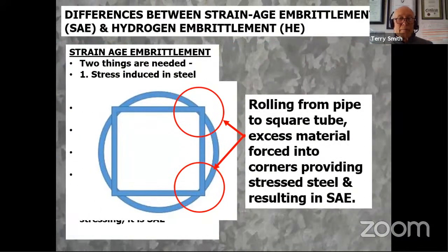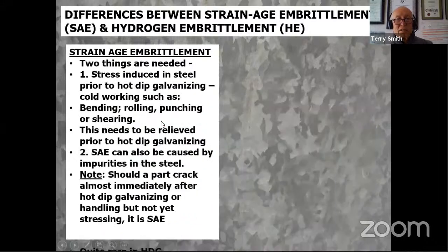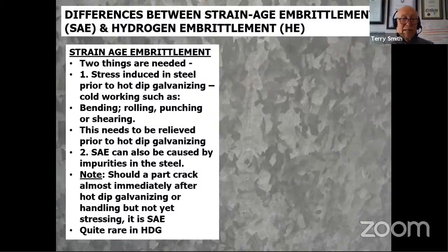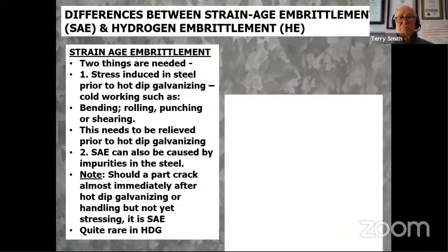when they produce square tubes, they take them and roll them from a round tube. And this particular tube had rolled more material into the corners because the natural dimensions of the square tube were less than the perimeter distance of the round tube. And that created huge stress in the corners, which obviously was relieved during the galvanizing process. So it's quite rare in galvanizing. I've only seen it twice in the 30 years that I've been involved in the industry.